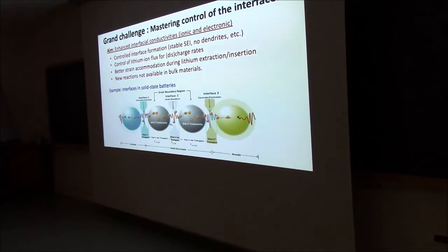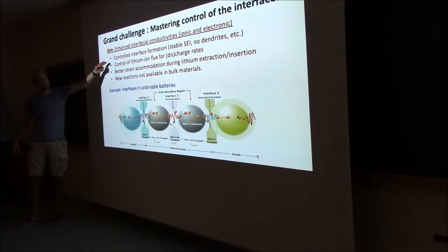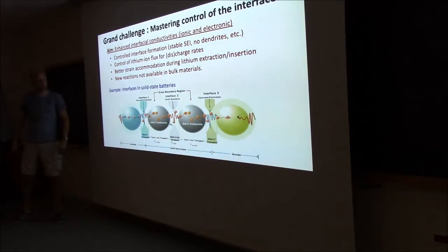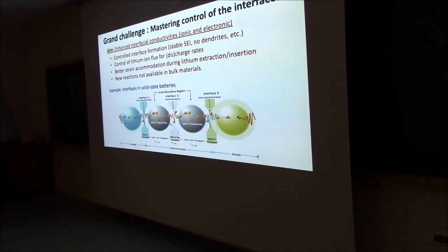These interfaces are crucial. So the aim is to use the control that we have to enhance the conductivities at these interfaces, ionic and electronic conductivities, and to control these interface formations. You don't want any dendrites. You want to control the flux of the lithium ion moving back and forth so that this can happen very fast. You want to have good strain accommodation. You can imagine if lithium goes in and out, the crystal structure will deform a little bit, so you want to take care of that. Because if this goes extreme, your material will always crack.